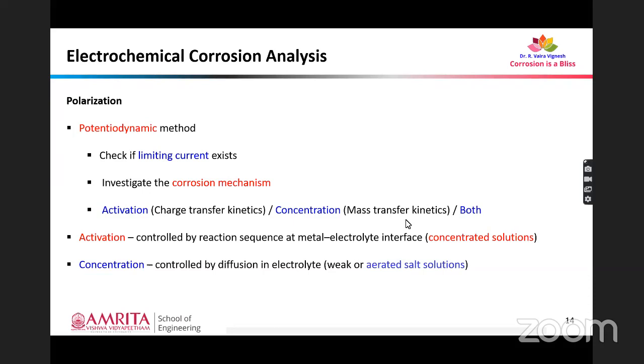So in activation based kinetics, the corrosion rate is controlled by the reaction sequence at the metal electrolyte interface. And in concentration kinetics, the reaction is controlled by the diffusion in the electrolyte. So this happens in weak or aerated salt solution. Okay, and activation based kinetics takes place in concentrated solutions preferably.